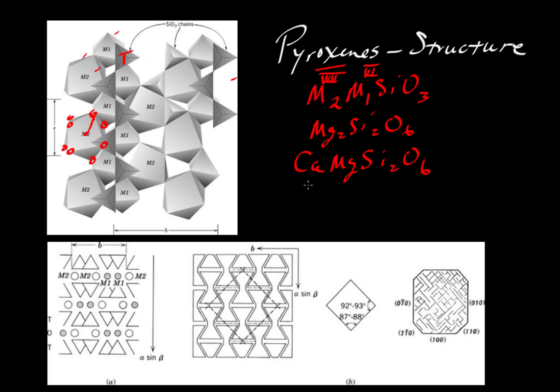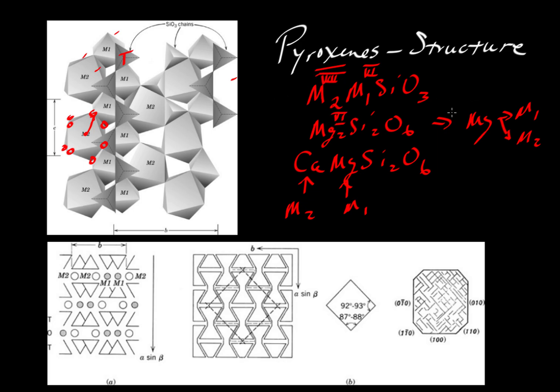In the case of diopside, the calcium — the larger cation — would be in the M2 site, and Mg is in the smaller M1. For the case of enstatite, the magnesium is occupying both the M1 and the M2 sites. For enstatite and ferrosilite, all of those magnesium atoms will be in six-fold coordination, so this eight-fold part is not necessarily fixed.